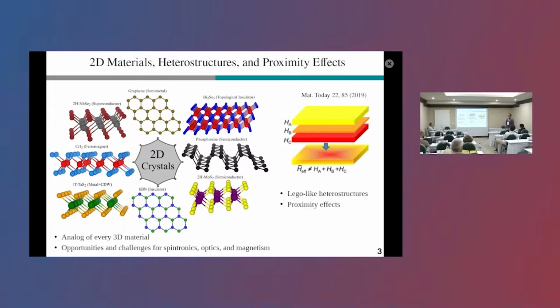So for example, if you look into such a tri-layer structure, then the effective Hamiltonian will not just be the sum of the individual ones, but rather it can be heavily modified by proximity effects. And the prototype material that one typically considers is graphene because it has a weak spin-orbit coupling. Actually, you can say it's roughly absent. And it also has no magnetism in it.